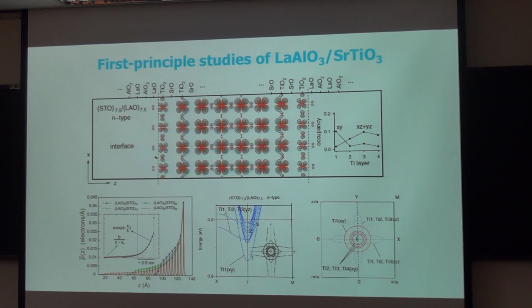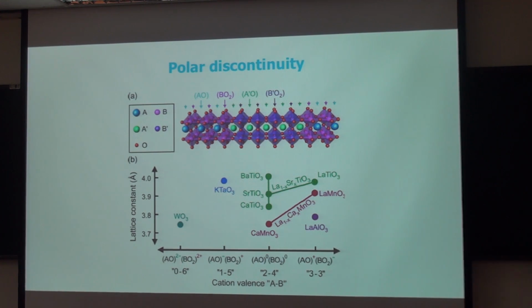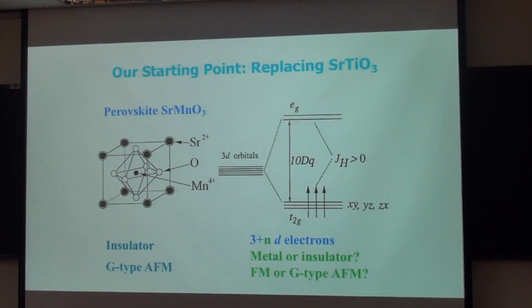well as possible superconductivity. Since the polar discontinuity is widely observed in transition metal oxides, this tells us very important information. That is, we can choose the A site and the B site ions to introduce various kinds of polar discontinuity, and we can study the charge transfer and its consequence on the magnetic order and electronic reconstruction. So our first work is starting from here. We just replace the formerly experimentally observed STO with a magnetic perovskite.